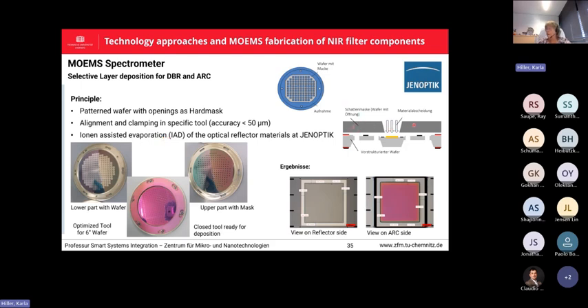We use a mask wafer, which is also a patterned silicon wafer with an opening. And we clamp this wafer together with our wafer, which is pre-patterned. And here we have the tools to do this. So this is a metal base wafer where we adjust the wafer we want to deposit. Then we have the mask wafer, again in a metal ring. We bring the two rings together. We have to align them using alignment marks, and then they are mounted together in this tool.